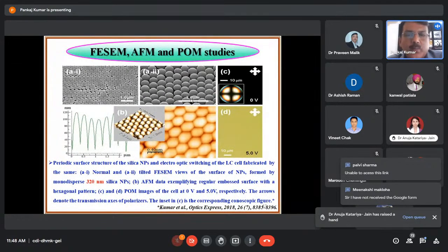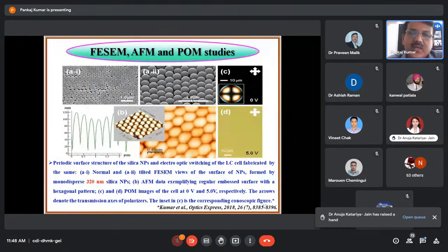So in figure B, you can see AFM data exemplifying a regular embossed surface with a hexagonal pattern. In figures C and D, POM images of the cell at 0 volt and 5 volt, which I have discussed. The arrows denote the transmission axes of the polarizers. The inset in figure C shows the corresponding conoscopic figures. So all these FESEM and AFM data show a very good coating of the nanoparticles on the substrate.